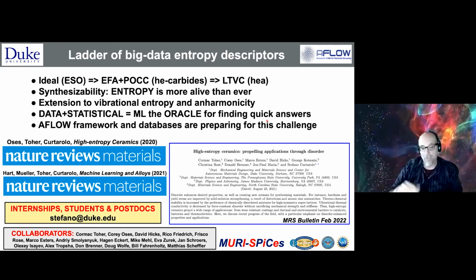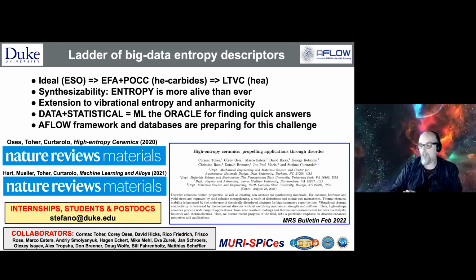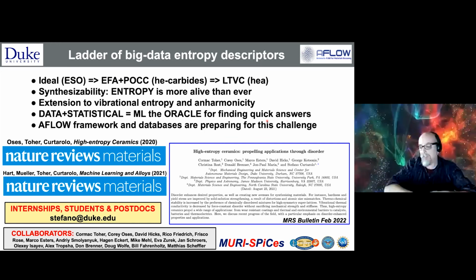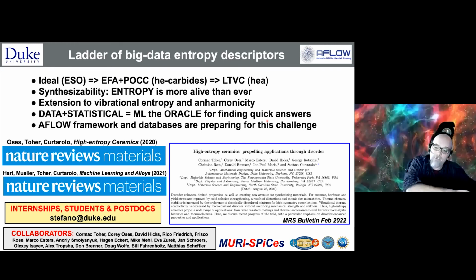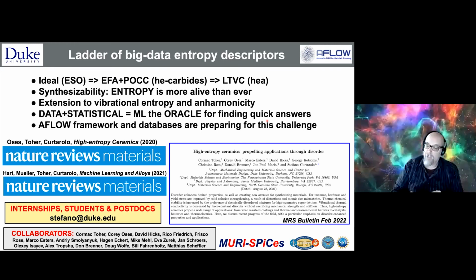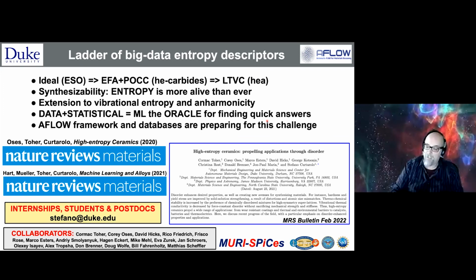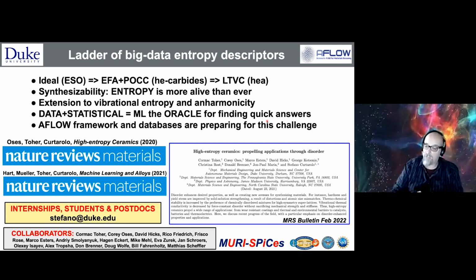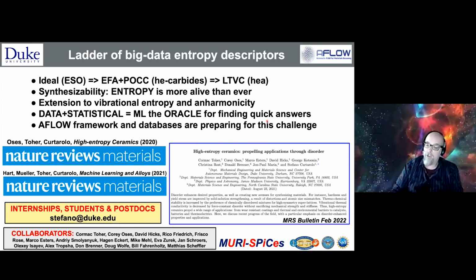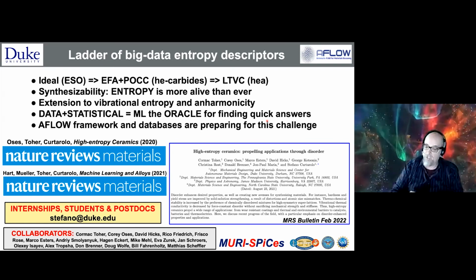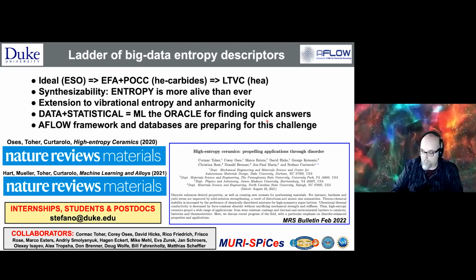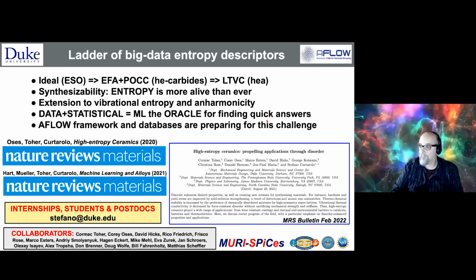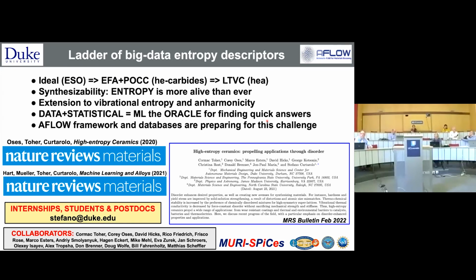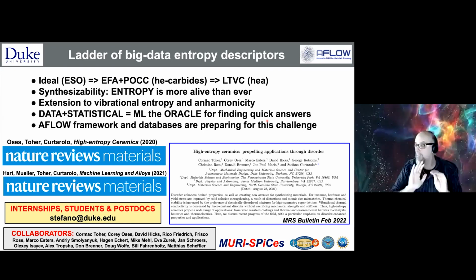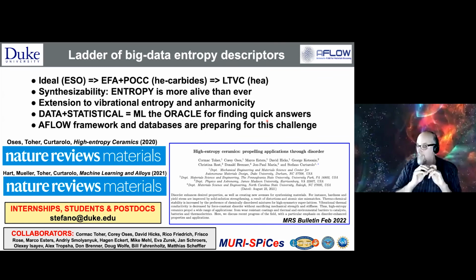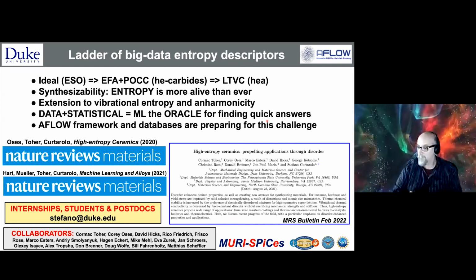We increase the number of species, and then we increase the temperature, and then we find that this material works, this material does not work. And then on the materials that do work, we slowly reduce the temperature, and we do the analysis that you're mentioning to see if it's really entropy driven or if there is an enthalpy, local enthalpy contribution. That's correct. We do this. Okay, thank you. But we discover only for oxides. We have not discovered for carbides. That's the answer. Okay. Thank you.